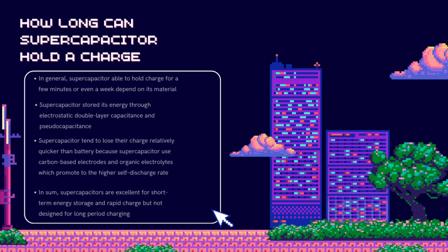Most supercapacitors are made out of porous carbon material, commonly used in double-layer capacitors. Due to the immense surface area, the ion absorption is relatively high and the amount of charge stored per volt is also high. However, surface functionalities and impurities present in the carbon can lead to a higher self-discharge rate. And organic electrolytes allow for a wider voltage range, increasing energy density, but typically have lower ionic conductivity and are sensitive to moisture contamination. This accelerates degradation and self-discharge. Therefore, supercapacitors are excellent for short-term energy storage and rapid charge, but not designed for long-period charging, as they have a high self-discharge rate. Next slide.